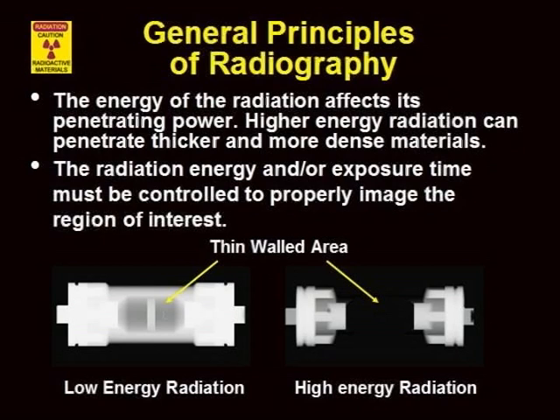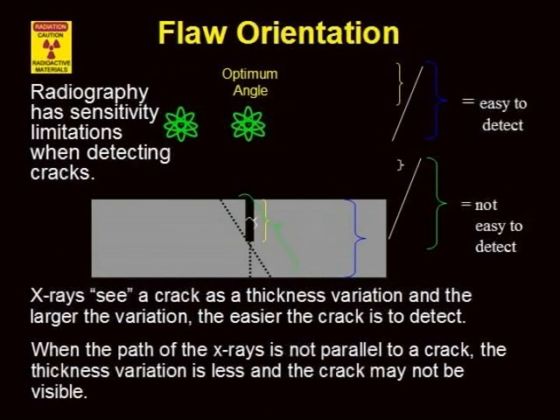This slide illustrates the effect of varying the energy to create two different exposures of the same test article. The thin-walled area becomes completely overexposed when using the higher energy necessary to reveal the details of the thicker-walled regions. When radiography is used for crack detection, the method responds to the crack as a change in thickness. The larger the change in thickness, the easier it is to detect the crack. Since cracks appear thick in only one direction and thin in an orthogonal direction, it's important that the direction of the x-rays be parallel to the crack, thus presenting the greatest effective thickness change. This sensitivity limitation makes it difficult to detect cracks that are not aligned directly along the line of sight of the x-rays.